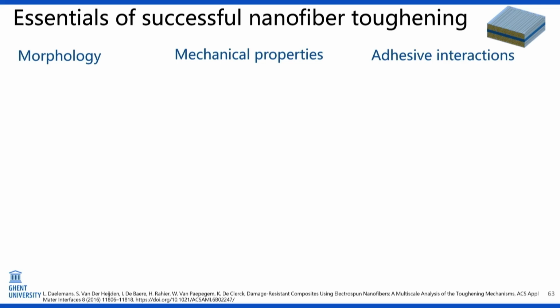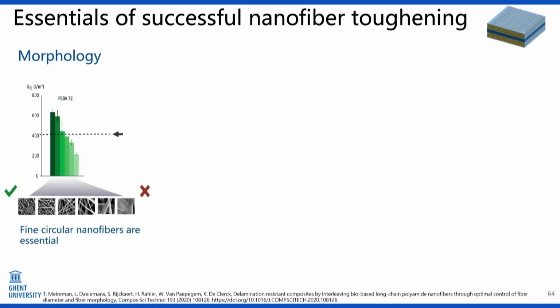There are many things that you need to take care of. The morphology of the nanofibers is important, the mechanical properties need to be optimized well, and you also need the proper adhesive interaction. For instance, we've shown that fine circular nanofibers are essential. If you have coarser fibers or ribbon-like fibers, you actually even have a negative effect. You even end up lower than the neat epoxy, with lower toughness values.